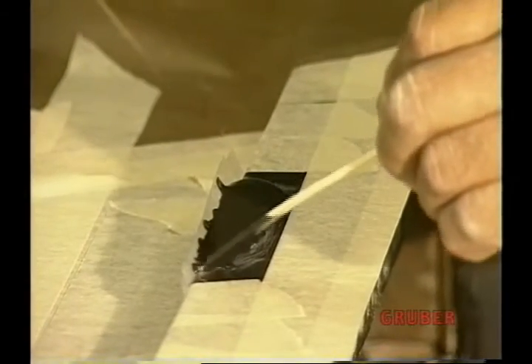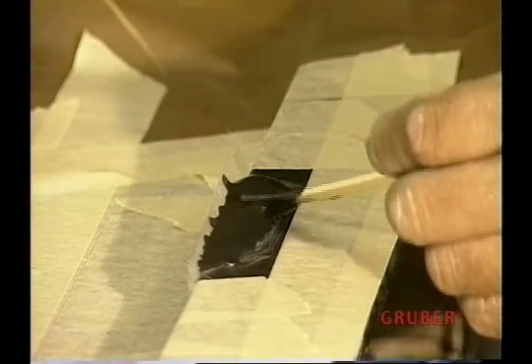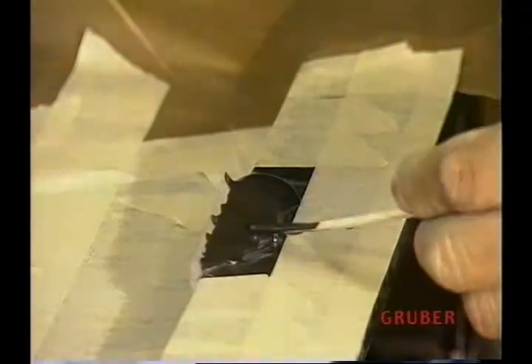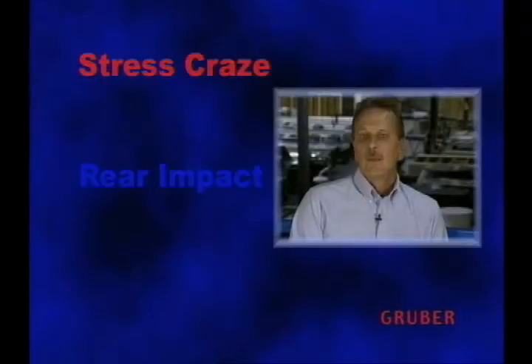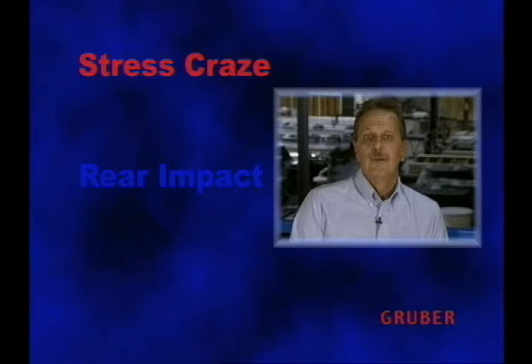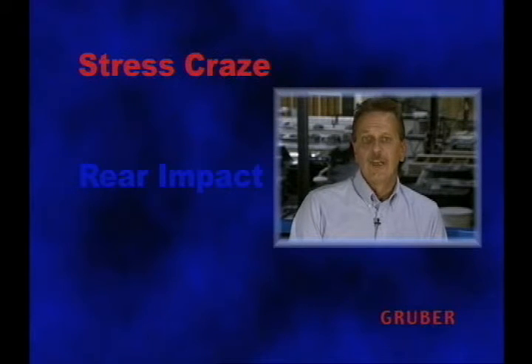The area must be overfilled to compensate for shrinkage that will take place during the curing process. It is also necessary to extend material beyond the repair area to allow for lateral shrinkage. We have now replaced the gel coat, and we'll cover the finishing of these molds at the end of the next section.